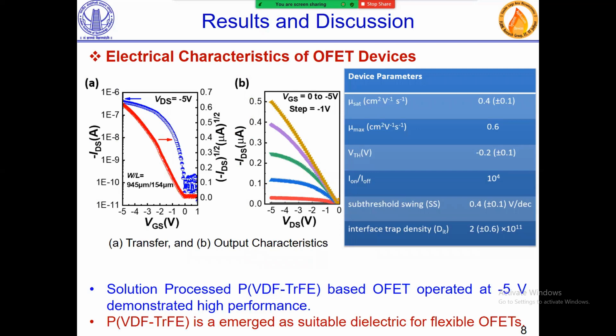These are the electrical characteristics of my fabricated OFET device. These transfer and output characteristics clearly show that the device shows p-type behavior. From these output and transfer characteristics, we are able to extract various parameters like mobility, which is 0.4, maximum mobility 0.6, threshold voltage minus 0.2, current on-off ratio 10 to power 4, sub-threshold swing 0.4, and interface trap density 2 into 10 to power 11. Solution processed PVDF-TrFE based OFET operated at minus 5 volt demonstrated high performance. PVDF-TrFE has emerged as a suitable dielectric for flexible OFETs.